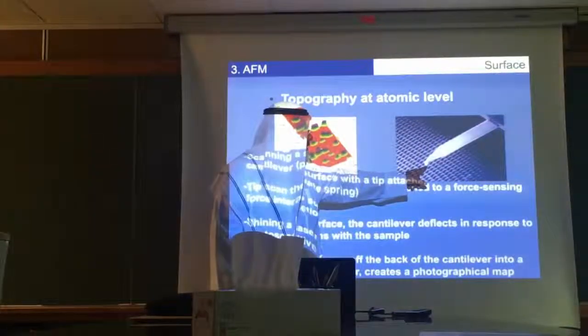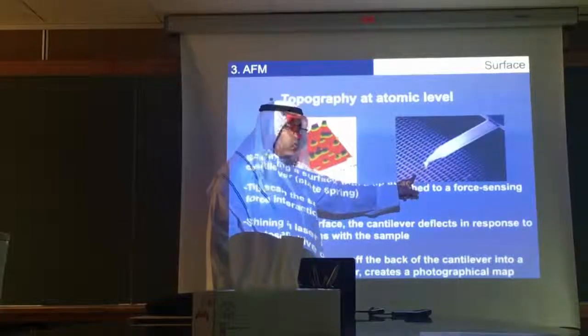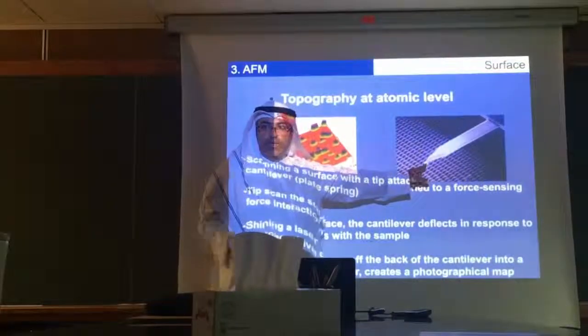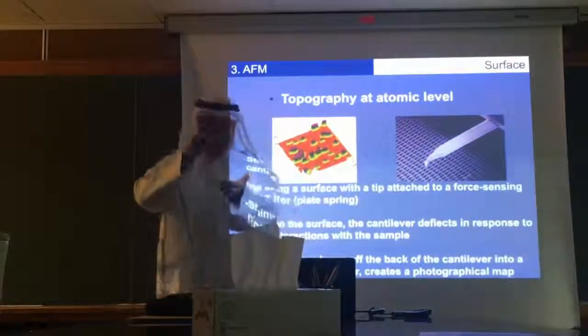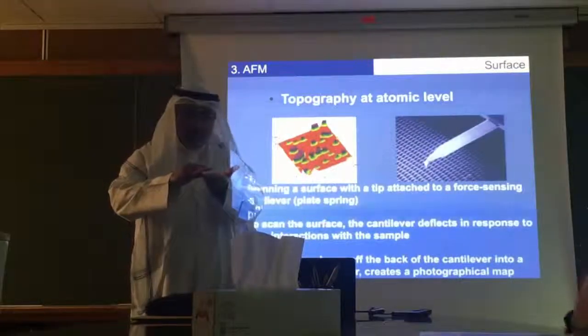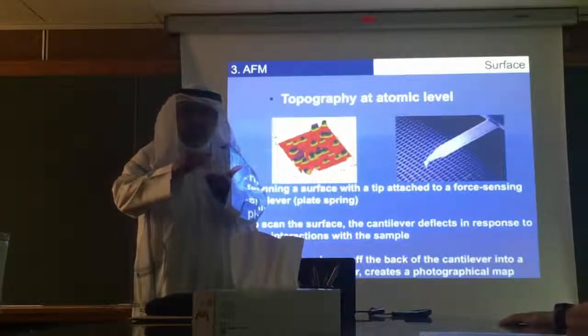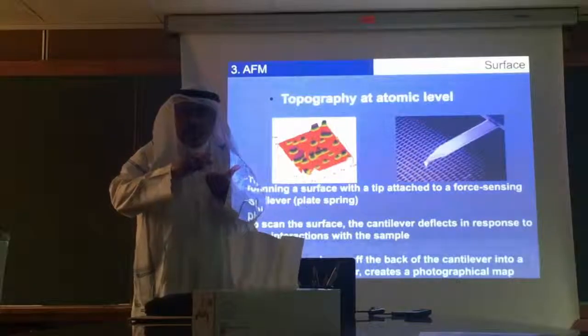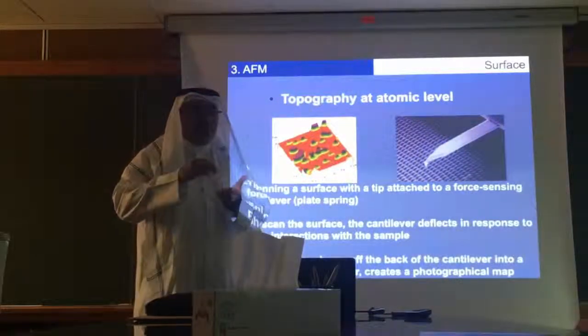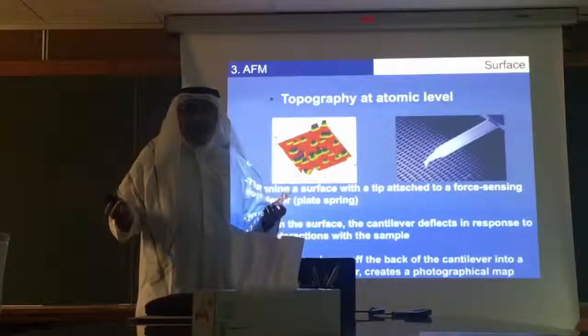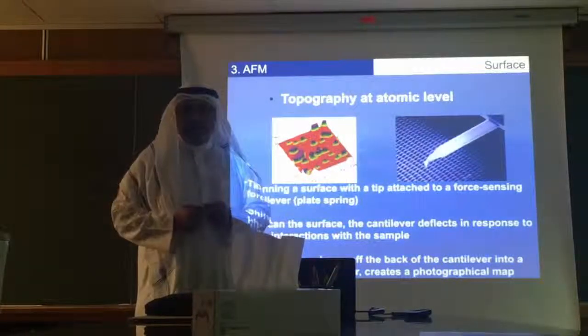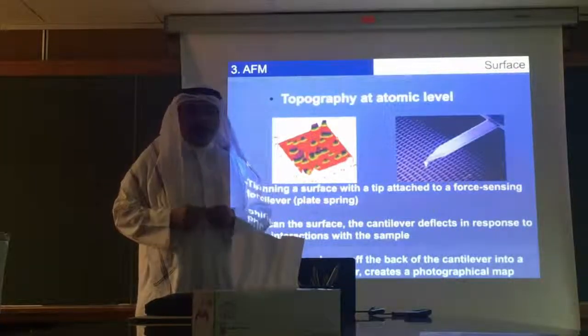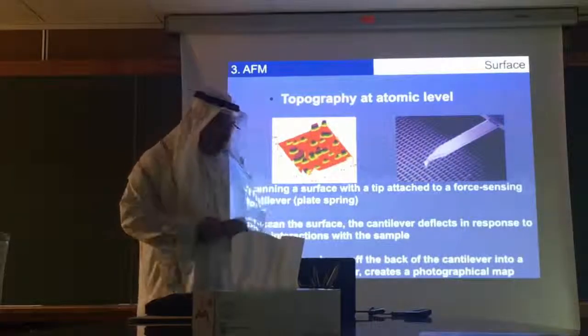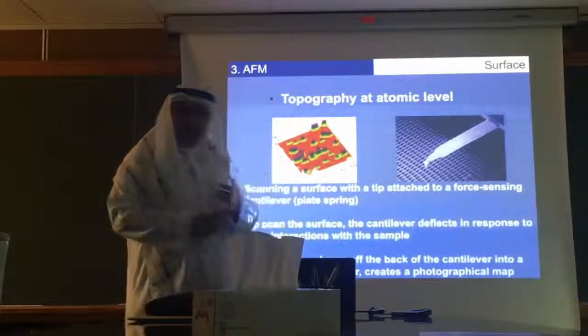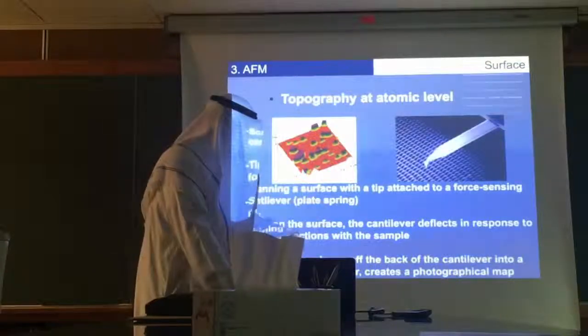So if I have a material and I want to know what is the interaction of this material or this material, I coat my tip with the material that I want, and then I just bring it close to the surface to start feeling the attraction or repulsion. But I don't allow it to touch the surface. And from the attraction and repulsion, I can figure out what is the van der Waals interaction between these two materials, whether they like each other or they hate each other. You can do the magnetic properties also by the same method.